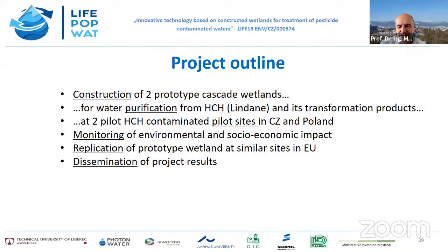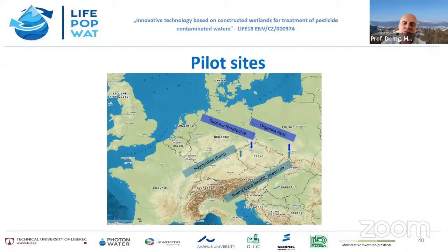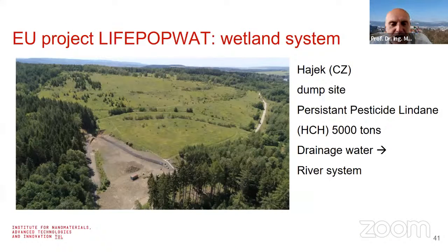One of the sites is here in the Czech Republic, another is in Poland, and of course we do some other activities and dissemination. These are the sites on the map of Europe. At the site called Hájek in the Czech Republic, the contaminants originate from the chemical factory Spolana, and the product was transported in the 1960s and 70s to this Hájek dump site, which I show in the picture here. It was just stored randomly distributed in this relatively big area. But nowadays the drainage water from the site contains a lot of these persistent organic pesticides, HCH, the total amount which is on the high side is about 5,000 tons. Of course, this drainage water goes to the river system, and it is able to contaminate the river system around.